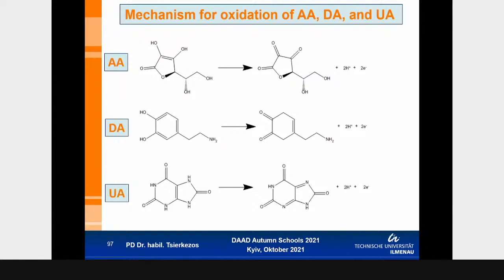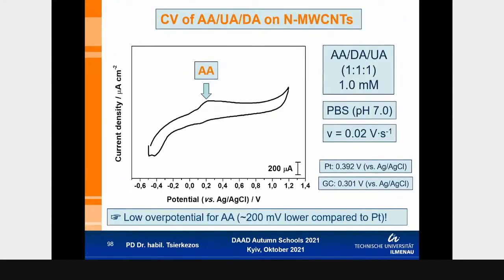The electrochemical process which takes place for all of these molecules leads to 2 electron and 2 proton transfer. We tried at the first step to oxidize all of these compounds in one step in the same solution on nitrogen-doped carbon nanotube without gold. So we add at the beginning ascorbic acid, and we observe a peak at about 0.2, which is attributed, of course, to the oxidation of ascorbic acid.